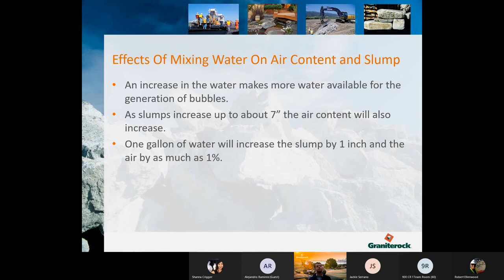So, effects of mixing water on air content and slump. One thing to be cautious of if you're using large amounts of air entrainment is that increasing the slump will have a large effect on that. So increasing the water makes more water available for the generation of bubbles, meaning more air. As the slump increases to about 7, the air content will also increase. And 1 gallon of water will increase the slump by 1 inch and air as much as 1%. Air is a tricky thing to really nail down. The reason being most other components of the concrete, even how fast you spin the drum, changes the air content. So one thing to think about.